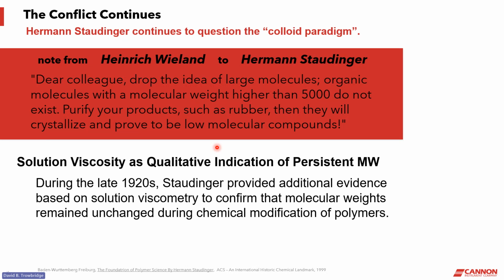Well, Staudinger did not take that approach, but he did want to do experiments to support his idea of large molecules, macromolecules. So his notion was that he would chemically modify these materials, and the idea was that the modification would cause a dissociation of the aggregates and destabilize the colloidal state, and the material would revert back to a low viscosity if it was in fact a colloidal system. He was expecting to see that the viscosity would not go down because he's thinking that the molecules were covalently bonded together in large sequences and forming a large molecule, and that is in fact what he found.